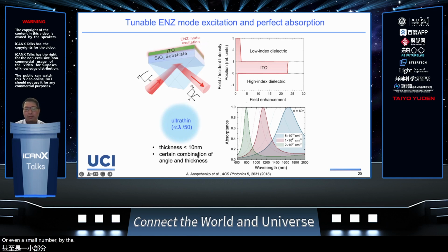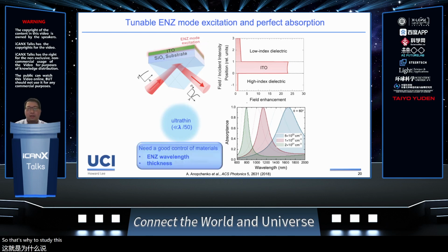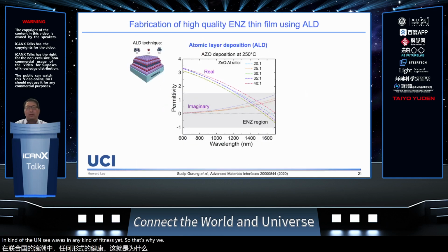But at the same time, you may need a certain combination of angle and thickness in order to excite this more efficiently. That's why, to study this ENZ property, we need to have good control of the material in terms of the ENZ wavelength and the thickness. So that's why we have been using a technique called atomic layer deposition to make this material. It's a layer-by-layer deposition technique, so you can really control the thickness quite precisely.